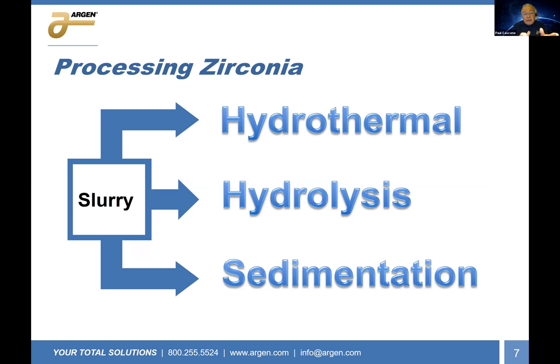Now, that slurry can be handled in a variety of different ways. Hydrothermal, as I just mentioned, means it goes into water and we impact it with basically just high temperature, and that drives the chlorine off and the water off as well. Hydrolysis can also be done, where you take that same slurry and you pass a current through it, and you can derive a certain quality of material from that. And again, these are very, very large batches.